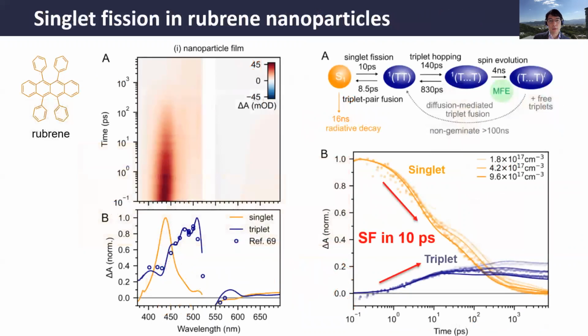So before addressing this question, we checked the transient absorption of these rubrene nanoparticles. This rubrene nanoparticle shows singlet fission with a time constant of 10 picoseconds, so it's definitely not intersystem crossing. After singlet fission, we further observe some evolution coming from the change from the strongly correlated triplet pair to the weakly correlated pair, and also spin evolution to other spin multiplicities.